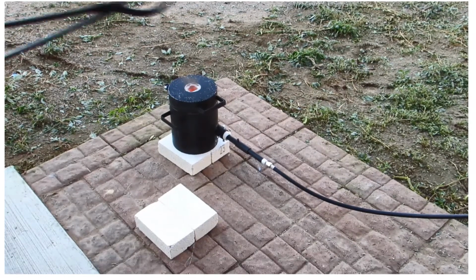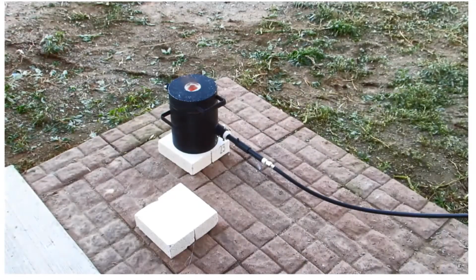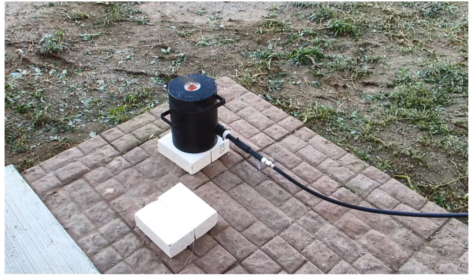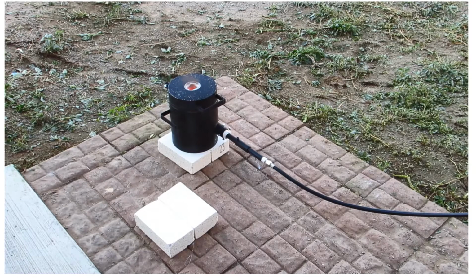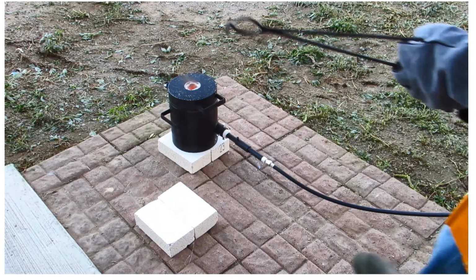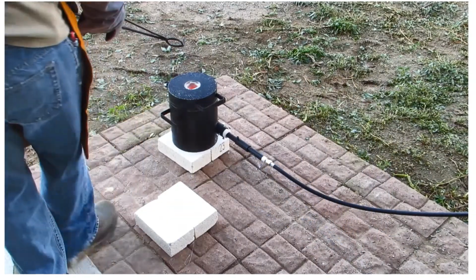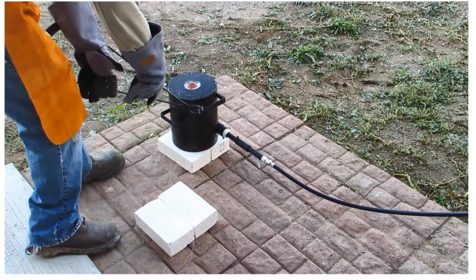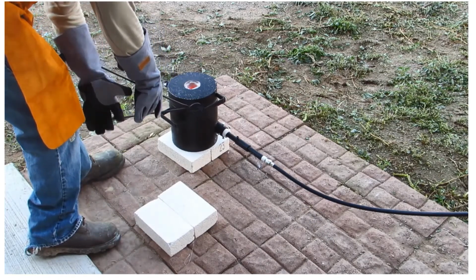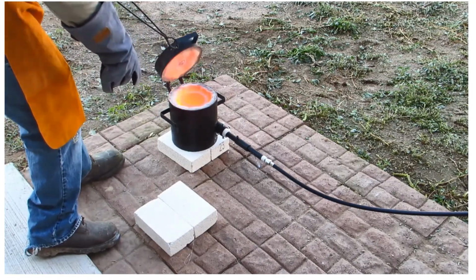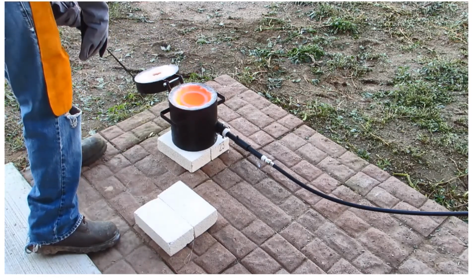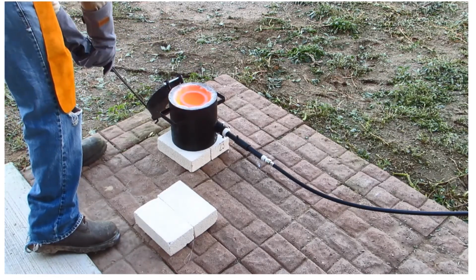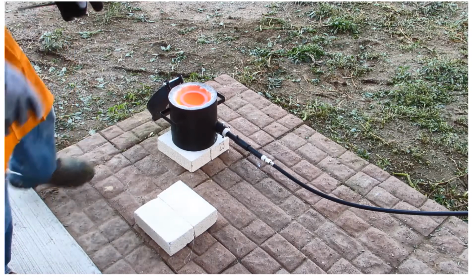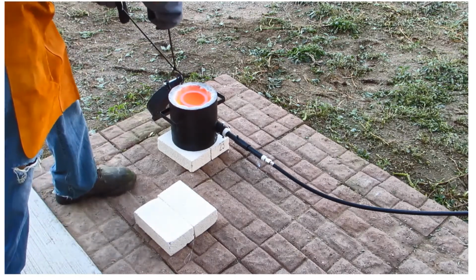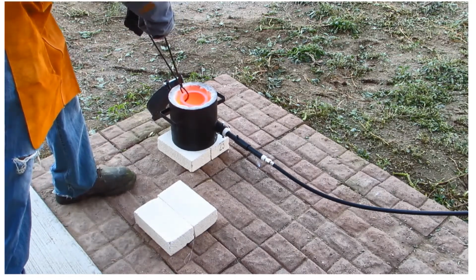All right, so we've melted our borax, and I'm cutting off the furnace by turning off the gas source. When you turn off a furnace, you always want to turn it off at the source of the fuel, so the fuel that's trapped in the line burns off. It's very hot, so I'm using tongs to open the furnace. I'm using small tongs to open the furnace and also to take the crucible out. I use different tongs to pour.